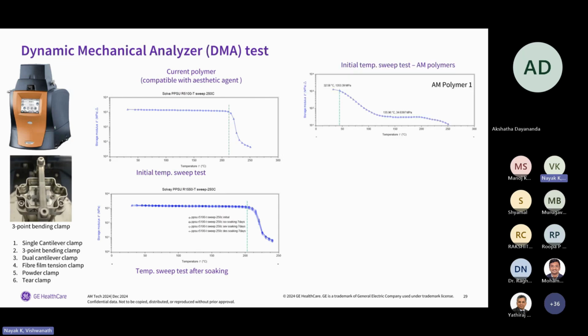It doesn't change. But when we tested one of the claimed polymers, that it is meeting ISO 10993-5, which is for cytotoxicity, we saw that this particular polymer has degraded, which means that the Young's modulus and the strength will degrade when you soak it. So this is not acceptable.